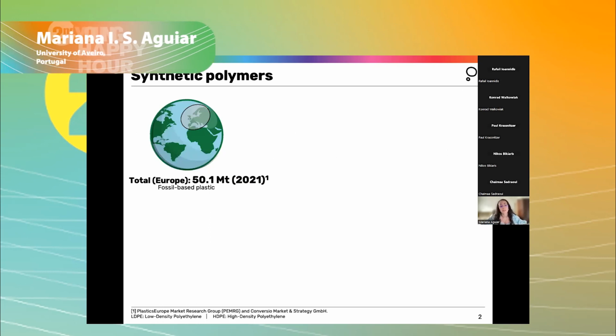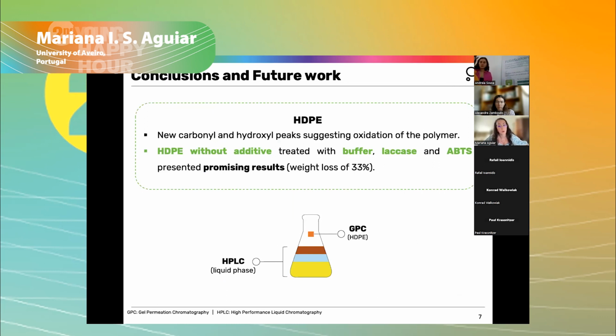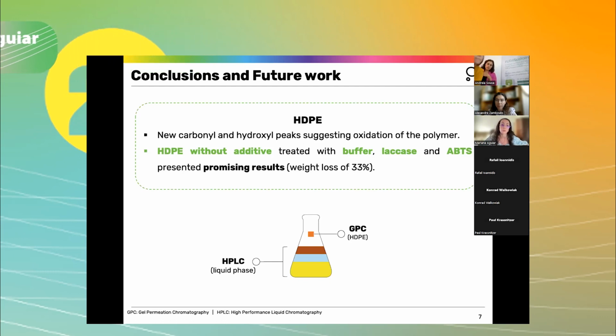Conventional plastics are synthetic polymers of fossil origin and resistant to physical, chemical, and biological degradation. In 2021, in Europe alone, 50.1 million tons of fossil-based plastics were produced, most of which corresponded to polyolefins such as polyethylene and polypropylene. Therefore, it was possible to see some promising differences on the treated polymers, especially on the HDPE without additive treated with buffer, laccase, and ABTS. In the near future, we will try to analyze the liquid phase through high-performance liquid chromatography to understand which monomers might be in the solution, and the recovered samples of HDPE through gel permeation chromatography to evaluate differences regarding the polymer's molecular weight and number.